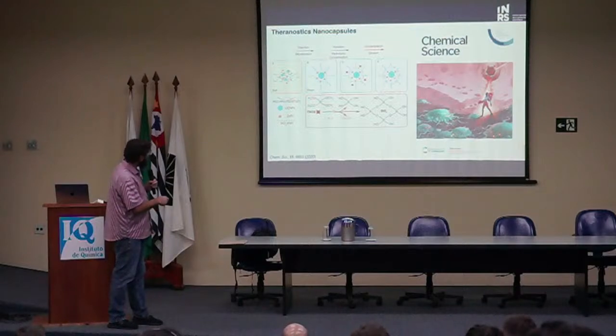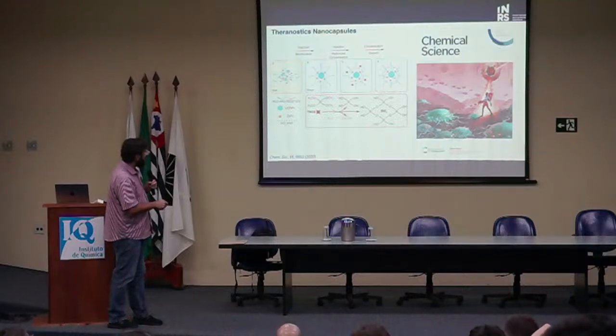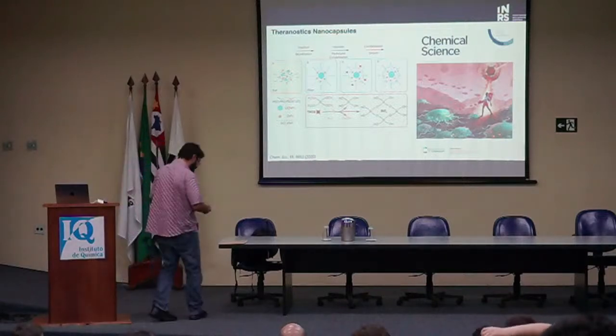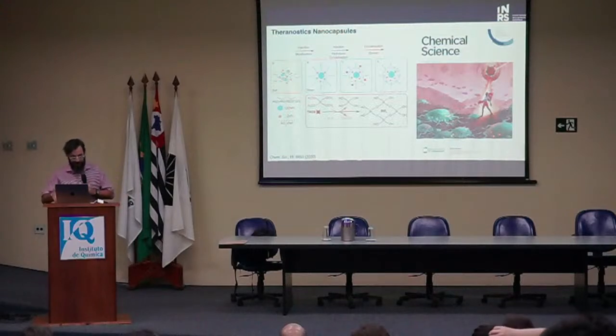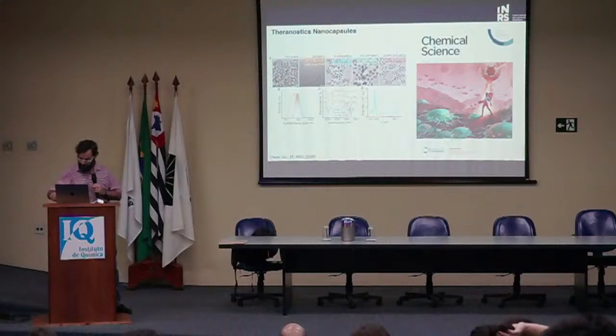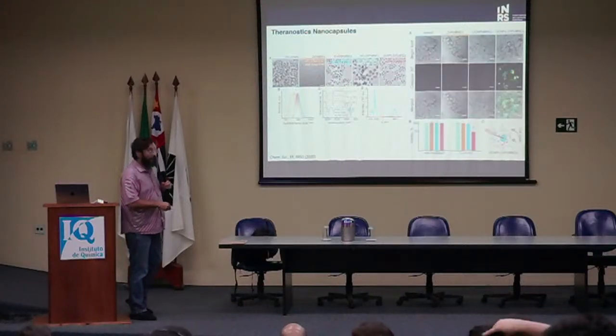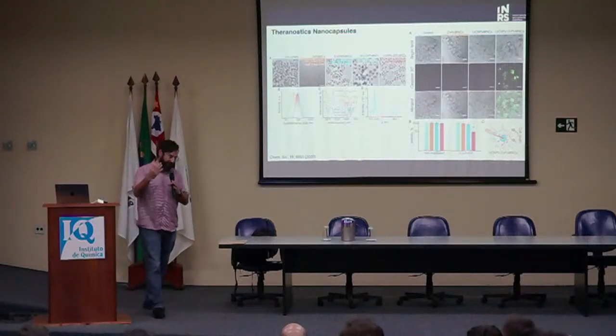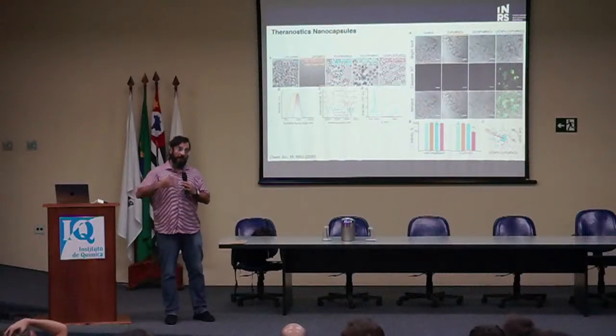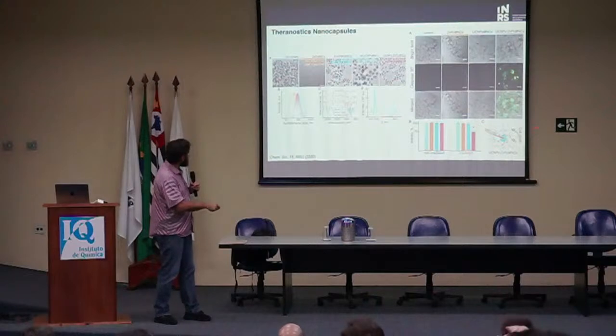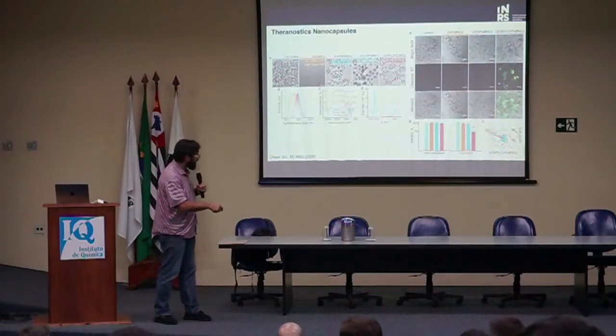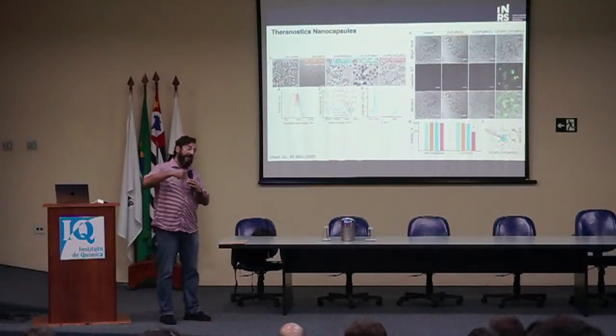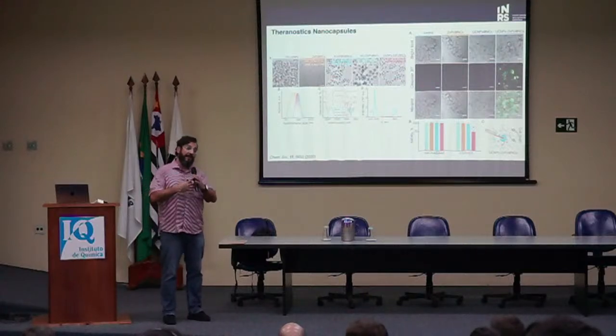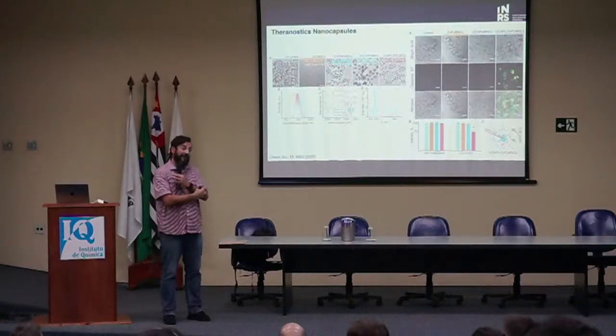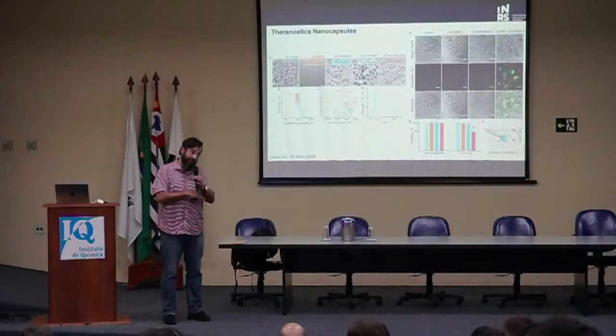And so one of the things I was really interested in doing is incorporating one upconverting nanoparticle and a photosensitive dye, zinc phthalocyanine. Okay, so zinc phthalocyanine is, as I mentioned, a photosensitive dye, and it converts light to reactive oxygen, and reactive oxygen is toxic to cells. And so this is something in cancer therapy called photodynamic therapy. The problem is that this zinc phthalocyanine, this ZnPc here, which is used in the clinic already, only absorbs visible light, which means that it can only be used on illnesses or malignancies that are on the surface, right? Because visible light does not penetrate your skin.